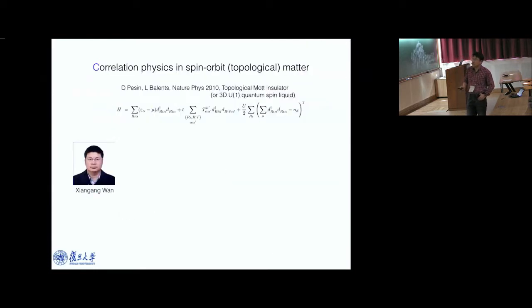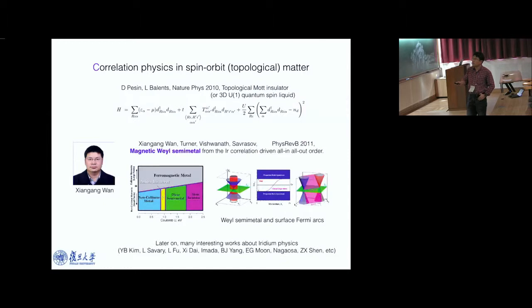So later on, Xiangang Wan from Nanjing University and his collaborators, Ari Turner, Ashvin Vishwanath and Savrasov from UC Davis, studied the magnetism of this family of materials very carefully. And in this first diagram, as they cranked up the Hubbard U in the ab initio calculations, with a certain set of magnetic order, they find that there is a regime that they called a Dirac metal. Really, because of historical reasons, this is a Weyl metal. They call it the Dirac metal.